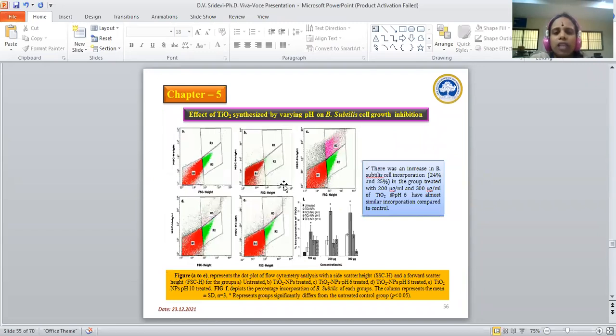The same result was observed with Bacillus subtilis on cell growth inhibition, that is almost 24 and 25% cell incorporation was observed when titanium dioxide nanoparticles synthesized at pH 6 were used at concentrations of 200 and 300 microgram per ml. This is shown in the histogram of figure F.